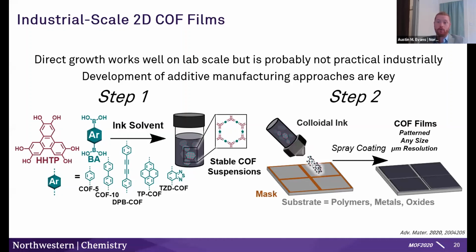So we realized, though, that having created colloidal suspensions of covalent organic frameworks, what we've really done is created a solution processable form of those materials for the first time. And so that led us to essentially taking these colloidally stable inks and just depositing them using a spray coating technique over a shadow mask to deposit, you know, patterned arrays. And this is a highly industrially relevant technique. You can scale it quite easily. And you can think about this sort of like spray coating a car. You know, if you want to paint a car, this is essentially how you would do it. Actually, the setup we use is a commercial airbrush, which is used for that kind of thing.